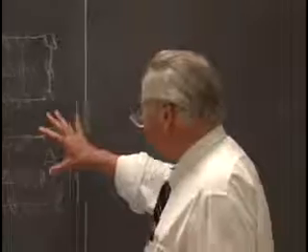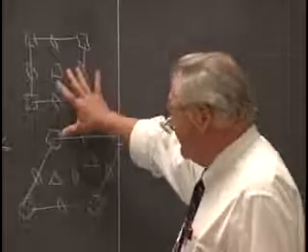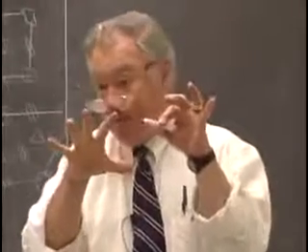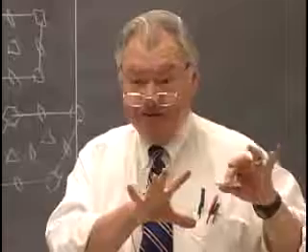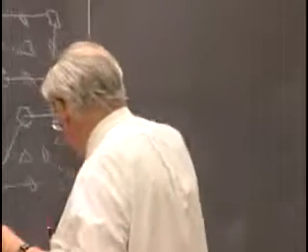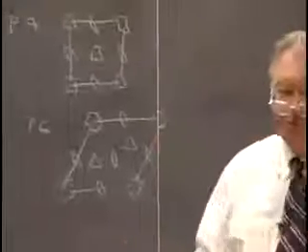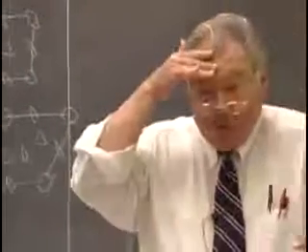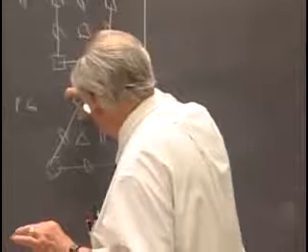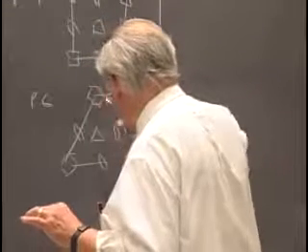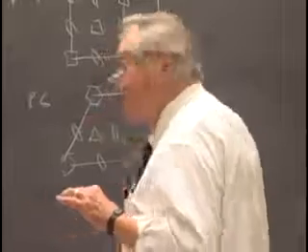Okay, I haven't drawn in any representative patterns, but let me remind you again, the pattern that is characteristic of every one of the plane groups is just the pattern that the point group that you've placed at the lattice point would produce, and that pattern is in turn hung at every lattice point of the two-dimensional cell. So even though the huge number of symmetry elements that's present in the higher symmetry plane groups is rather intimidating, you say, wow, how would one draw a pattern for that? The pattern is nothing more complicated than the pattern of the symmetry that you've placed at the lattice point, and all of these other symmetry elements arise to express relations between the motifs that you've placed at the initial representative